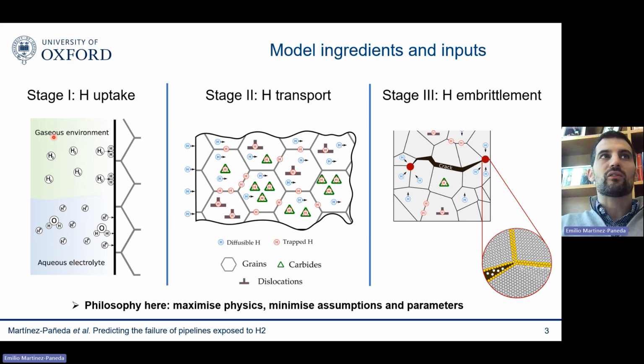So first, the ingress of hydrogen into the metal, then the diffusion of hydrogen within the metal and within the microstructure, and then finally the embrittlement process per se, the nucleation and growth of cracks due to the presence of hydrogen. And one thing that I want to emphasize here is that my philosophy is to maximize the physics. There's no fitting parameters, there's no strong assumptions. I'm basically reproducing as much as I can, resolving the underlying physical processes that describe hydrogen embrittlement. So we want to minimize assumptions, and we want to minimize parameters. This is a fitting-parameter-free model. There's no fitting parameters involved.